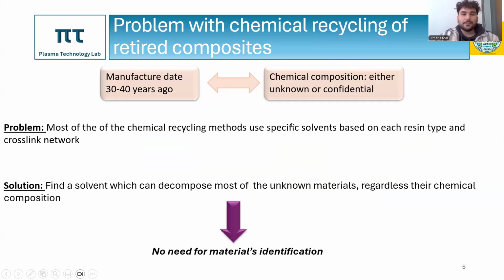And the first problem that we need to deal with when we start this research was that those retired composites that we wanted to decompose were manufactured like 30 or 40 years ago. In most cases, the chemical composition was either unknown or confidential. And here was the problem that most of those chemical recycling methods, they use specific solvents based on the chemical composition of the material. That's why we need to find a solvent which can decompose most of those unknown materials, regardless the chemical composition, so we wouldn't have to do materials identification.